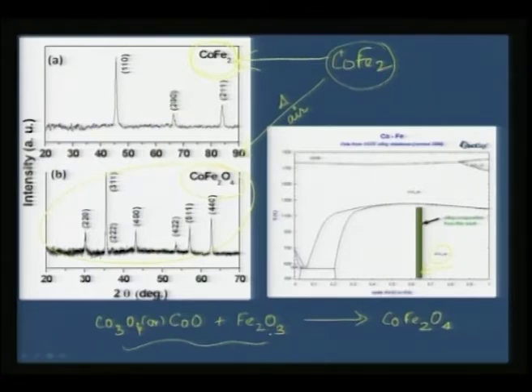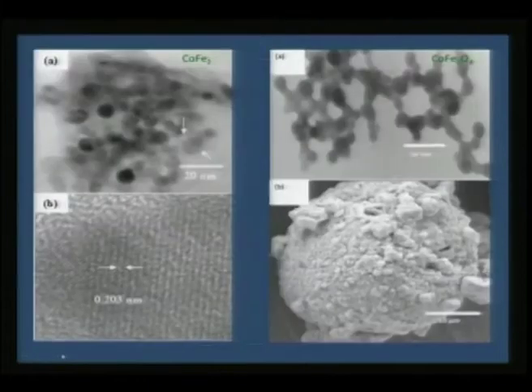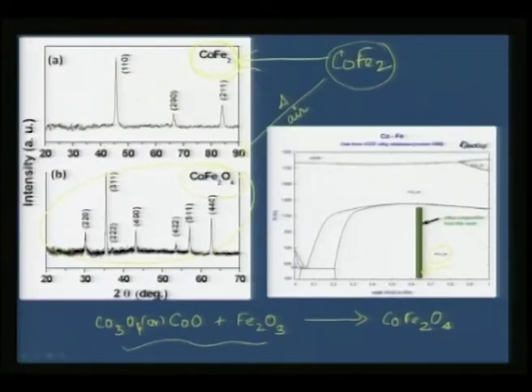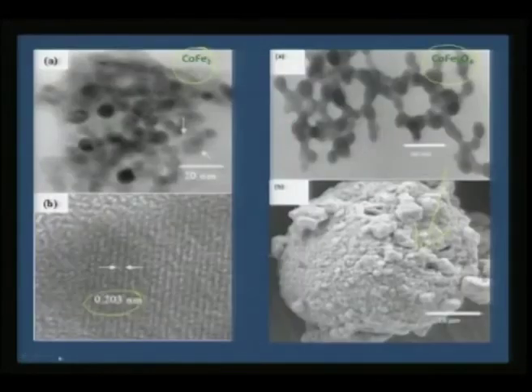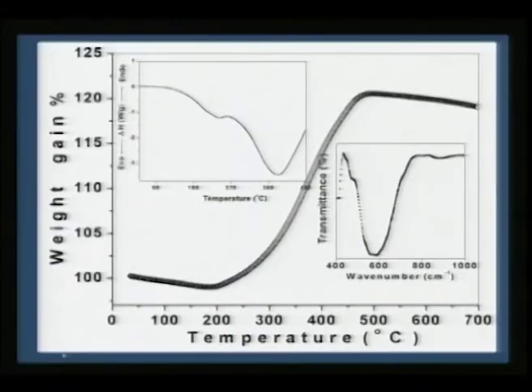So, this is the conventional way of preparing, but for the first time we could observe that cobalt ferrite can be made even using an amorphous alloy as a precursor. You can see here the morphology of the CoFe2 alloy, and this is the morphology of CoFe2O4, and this is the SEM pattern of the oxide powder that we can prepare. These are the CoFe2O4 nanoparticles which are prepared, and the dimensions of the lattice spacing exactly match with that of the CoFe2O4 phase.